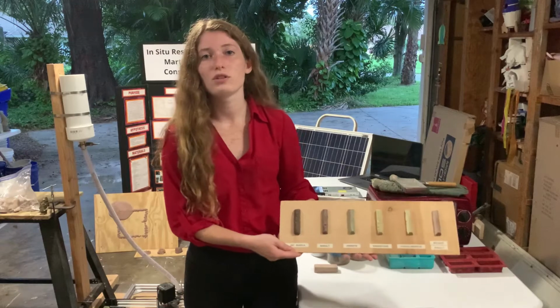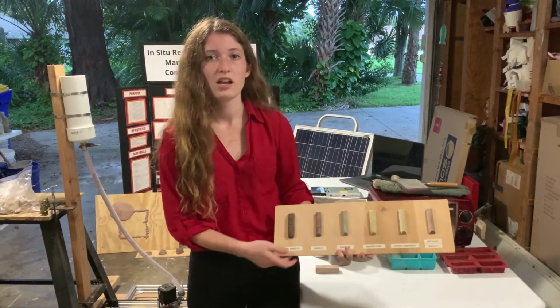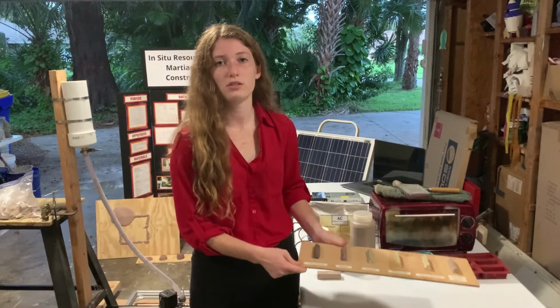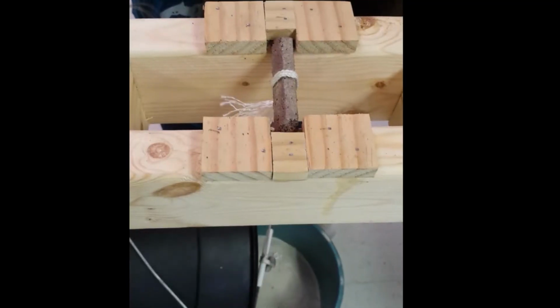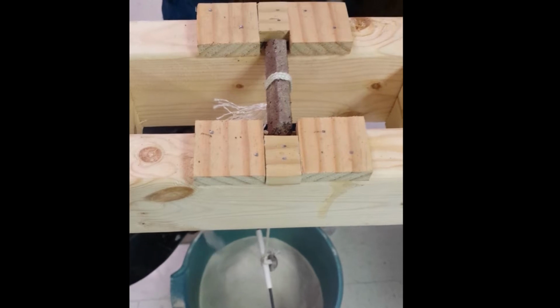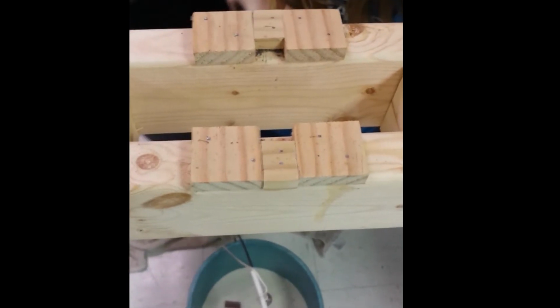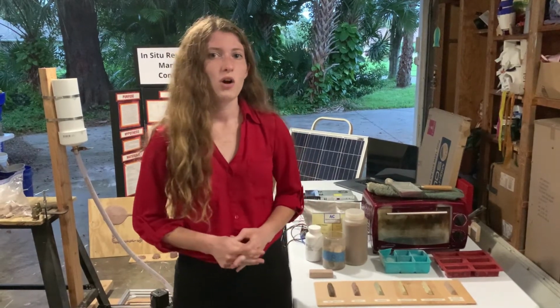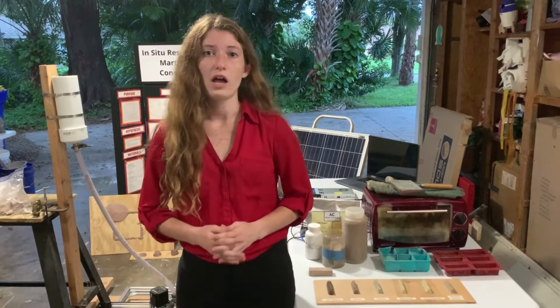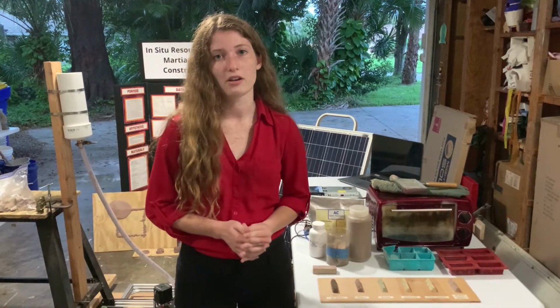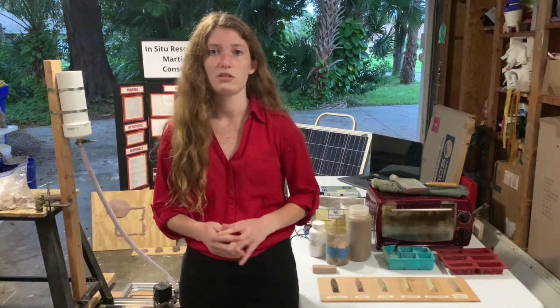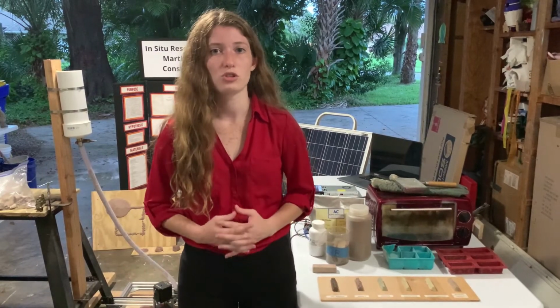And I tested these using a homemade tensile strength test in which the bars were placed between 2 pieces of wood and a string with a bucket attached was held from it. And sand was poured into this bucket basically until the bars snapped and the weight in the bucket was recorded. So I ended up figuring out that basalt actually made it the strongest out of all the aggregates, concluding that using soil rich in basalt would help make it stronger.